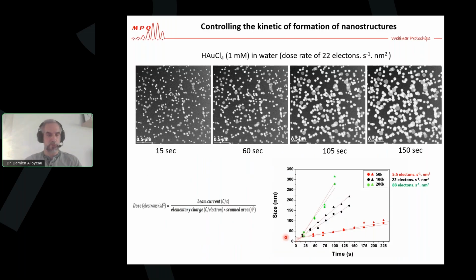So the first experiment that we did when we had this sample holder, 10 years ago now, we did this experiment with a gold chloride solution, 1 millimolar, in very low dose rate conditions. And here you observe the growth of well-faceted nanoparticles. And what is interesting is I show you here the evolution of the size of the nanoparticles as a function of time for 3 different magnifications. When you work in STEM mode and you increase the magnification, you put the same beam energy on a smaller area, so you increase the dose rate. And you see that when you increase the dose rate, we increase the growth speed of the nanoparticles.